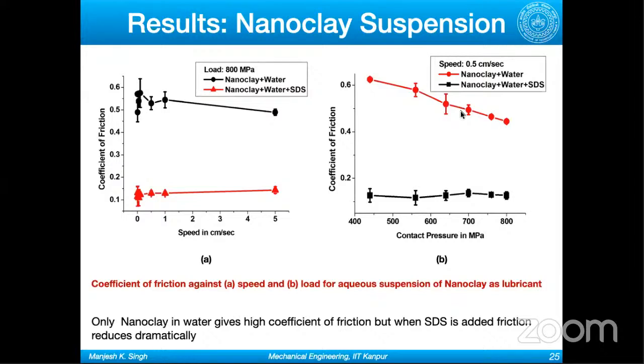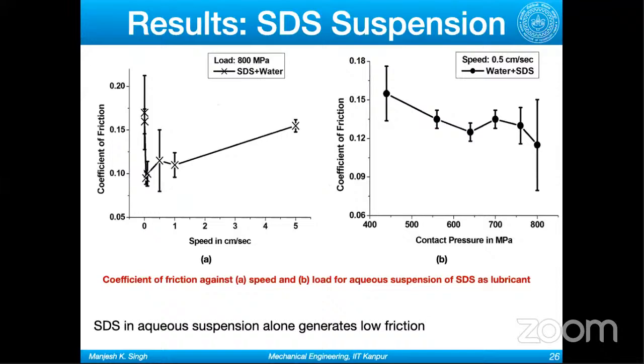So that made us interested in what the effect of SDS, or sodium dodecyl sulfate, is. What does it do? To check that, we did one experiment with only sodium dodecyl sulfate and water, so surfactant and water, and we also saw very low friction. I'll go back to these results later. So what we can say is, in the case of MoS2 plus water only, we are getting low friction. But with nanoclay plus water, we were getting rather high friction. But when we added SDS plus water, we are getting low friction.